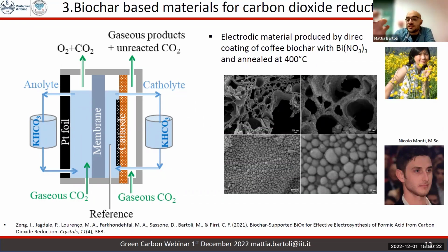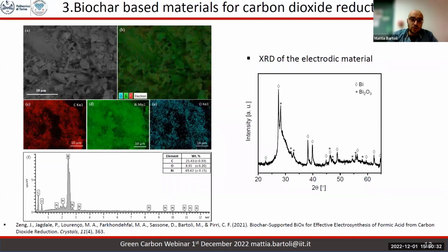So our carbon sponges made with coffee-derived biochar were deposited on a cathode surface, and we studied them for the reduction of CO2. As you can see from this characterization, the tailoring of the surface of the biochar was complete. Bismuth is covering everything, and we loaded a lot. And as you saw before, there is a core of metallic bismuth covered by bismuth oxide, thanks to the reaction that you saw in the previous slide, where the metal is reduced by consuming carbon, increasing the surface area. We reach a loading of bismuth up to 65%, at least on the surface. Of course, it's EDX, so it's a little bit lower, but that's another point.